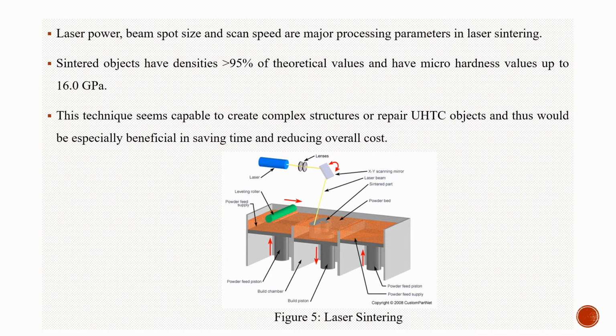Laser power, beam spot size and scan speed are major processing parameters in laser sintering. Sintered objects have densities larger than 95% of theoretical values and have micro-hardness values up to 16.0 GPa. This technique seems capable of creating complex structures or repairing UHTC objects, and thus would be especially beneficial in saving time and reducing overall cost.